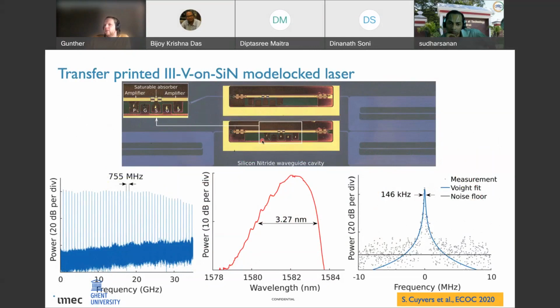Using this technique, we then built mode-locked lasers. In this particular project, the idea was to make very low repetition rate mode-locked lasers, so below 1 gigahertz repetition rate, for microwave photonics applications. And in order to realize such a low repetition rate, you need very long cavities. And here we exploit the very low losses in silicon nitride to form these low-loss cavities. So this was a first example of a sub-1 gigahertz III-V on silicon nitride mode-locked laser.